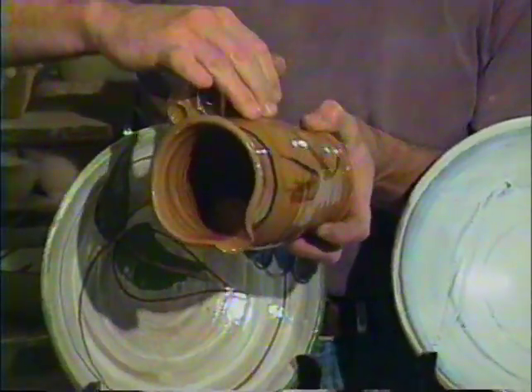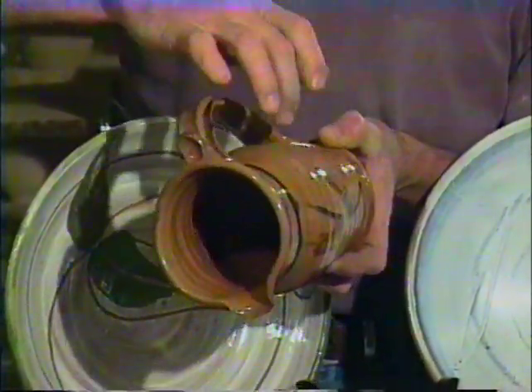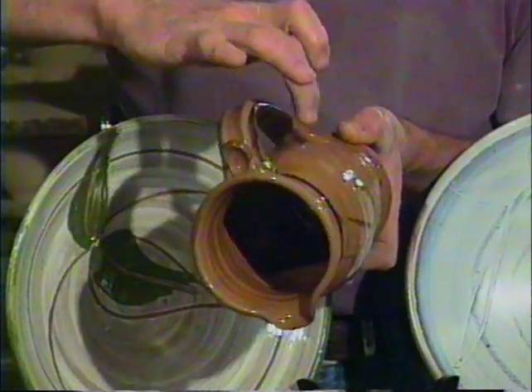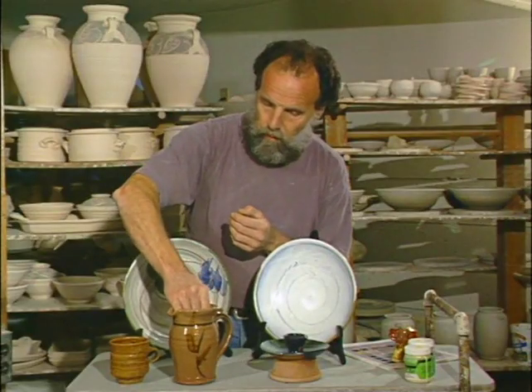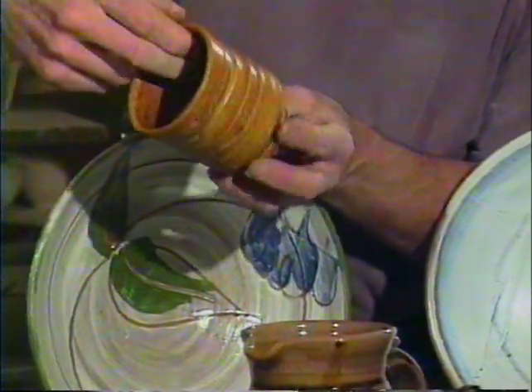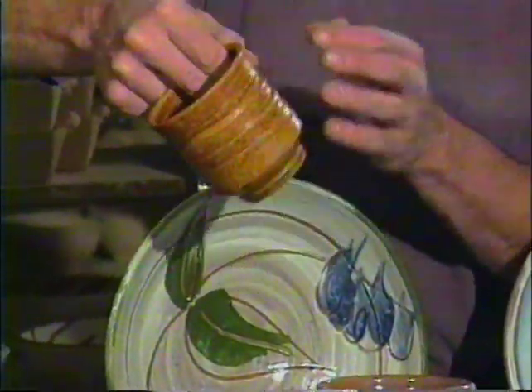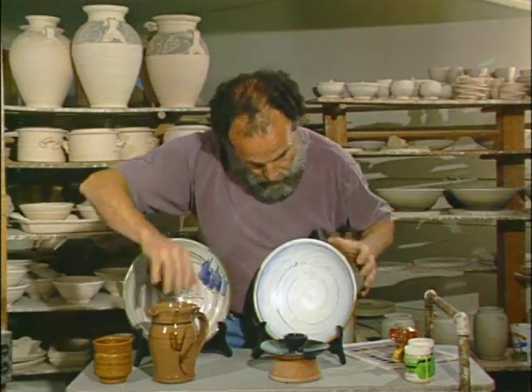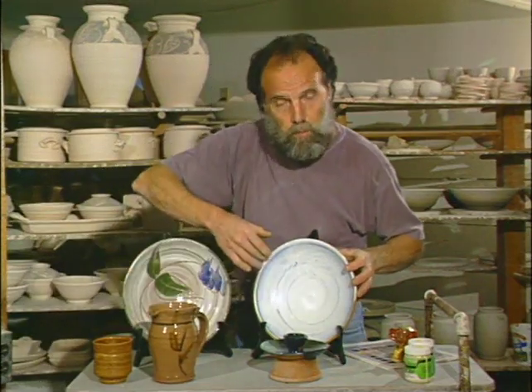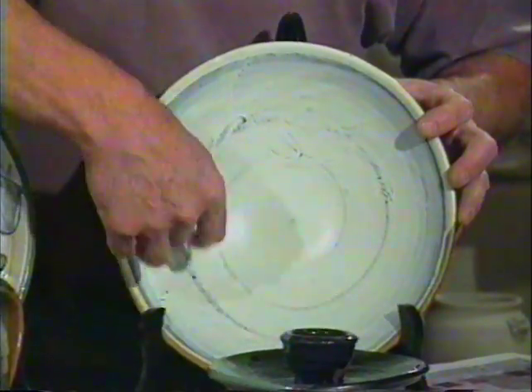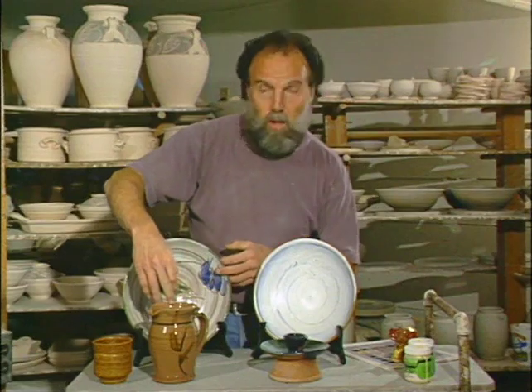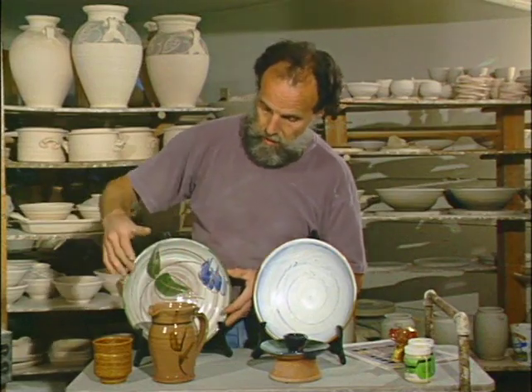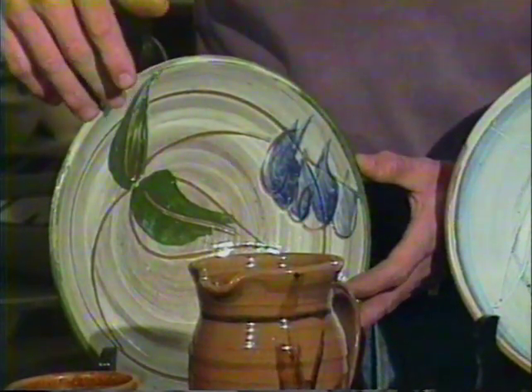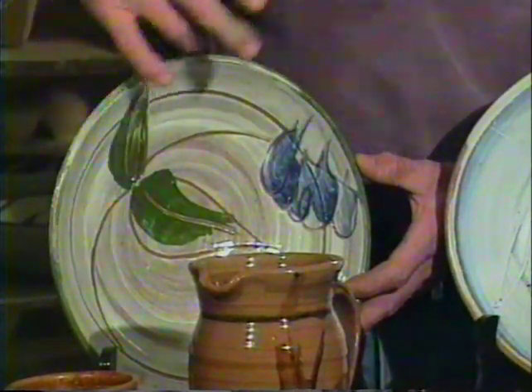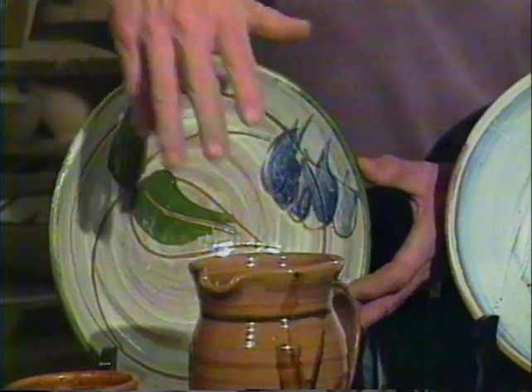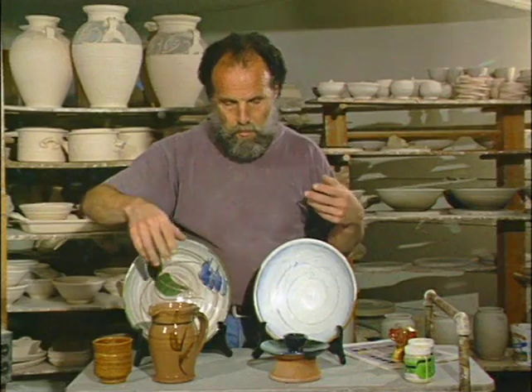This particular one, which is the base glaze that we're using in this program, is a clear, colorless, glossy glaze. By contrast, you see that we have a matte glaze here, much lower reflectivity to its surface. Quite a similar thing could be said about this one, which is an opaque white over a blue slip covering underneath. Clear glossy glazes are particularly suitable for the decorating techniques that we've emphasized in this program, because here we have the clear colorless glaze over the colored slips underneath.